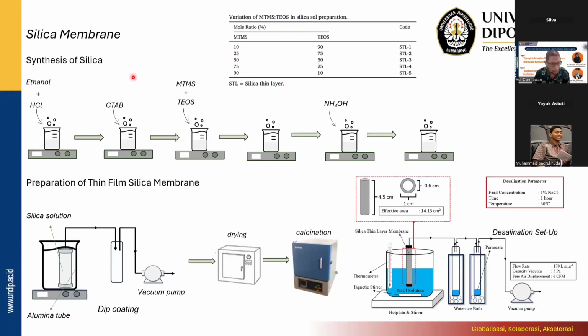The idea is the same, putting the silica on a support, but not like the GO. There I used a nylon support, but for silica I use an alumina support, because silica is very brittle and we can't use a flexible support like nylon. So the silica was coated on the surface of the alumina support. The desalination setup is quite the same. This is the feed, which is salt water, and I use a pervaporation system, in which the salt water is sucked by the vacuum chamber here, and the water vapor